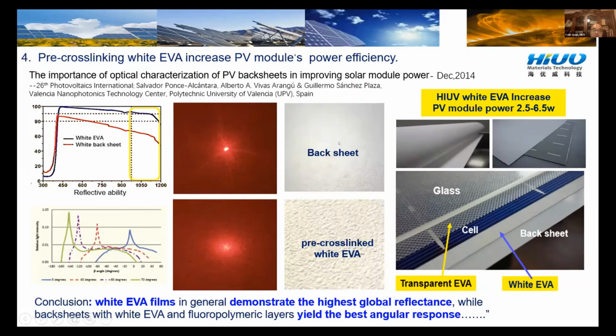And we also tested the backsheet and the pre-crosslink white EVA. This material looks like a low mirror reflection. They have a really nice angle response. Their reflected light is spread very widely. This can be reflected back to the module, okay? So the use of pre-crosslink EVA can generate more than 2.5 to 6.5 watts per module.